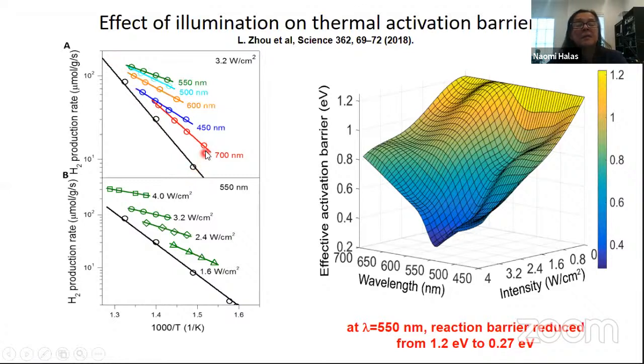I do the same thing at different temperatures, but I do it under illumination for several different temperatures. I try another wavelength and I do several different temperatures and I measure the barrier. I do another wavelength, et cetera, et cetera. And look, for each of these wavelengths, I change the slope of the line. So I'm changing the actual barrier to the reaction. And I find that at some wavelengths, I've changed the barrier a lot, some not so much. So I can actually map this out.